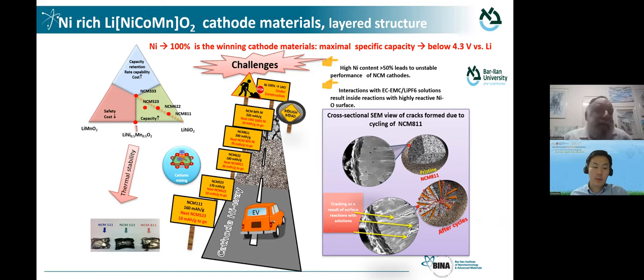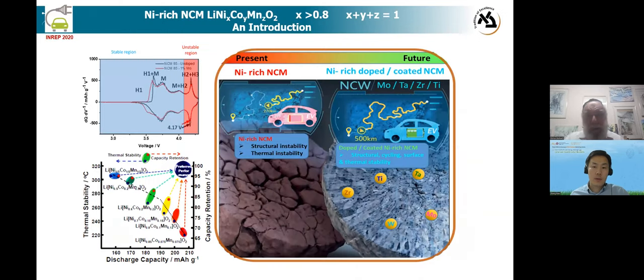But all our cathode materials, I'm not talking about the negative where the reactivity is obvious, but also the positive electrodes, are very reactive materials. When we have lithiated transition metal oxides, they are very basic and nucleophilic. So we have a lot of options for side reactions between the electrolyte solutions and the active mass, beyond the option of oxidation of the salt. Here we see the cracks, a cracked particle after cycling. And this is a major problem that we encounter here, disintegration of the active mass.